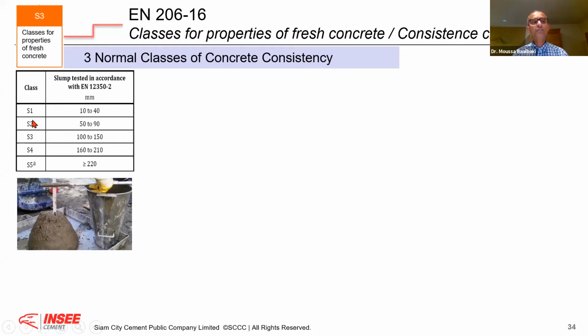So you see, you have different class of consistency, but as we know very well, in Sri Lanka, most of our concrete, if I take our ready mix, for example, more than 90% of our concrete are S4, at the highest class of consistency, S4. You see the S5 here, more than 220, this is not recommended. You see the small a is saying that it is very difficult to consolidate those concrete and to keep a good stability. Better to go below 220.